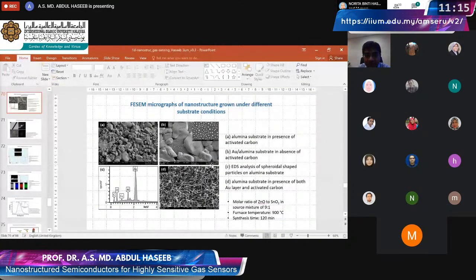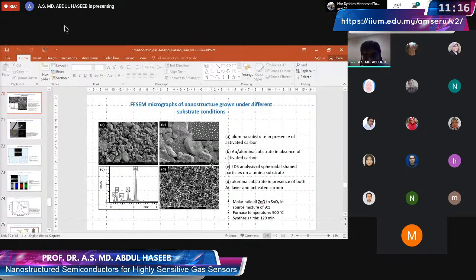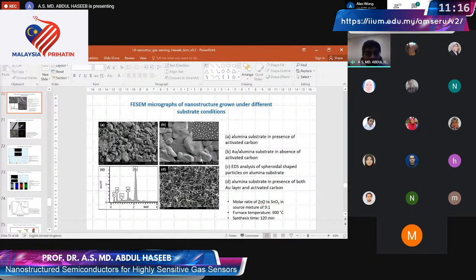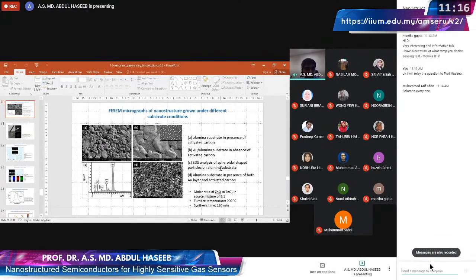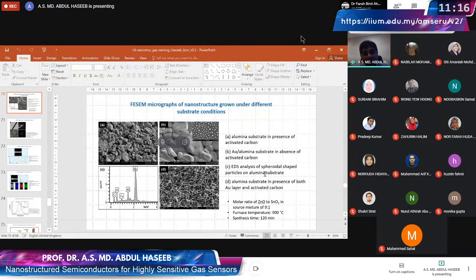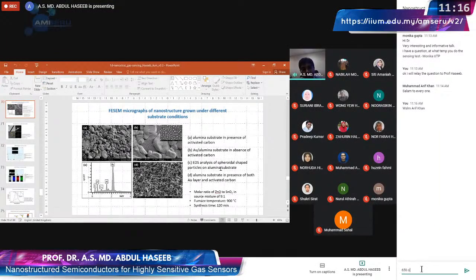Prof, there is one question from the chat. Hello, Prof. Very interesting and informative talk. At what temperature do you do the sensing test? The question comes from Monica from UTP. That is a very interesting, important question, and my apologies, I forgot to tell you this. If you saw some of the figures, the sensing temperature is high, because it has to be high in gas sensing with metal oxide semiconductors. We did the sensing in the case of titanium oxide at 650, because that was the optimum that we got. We get a high signal. We could go to other values, but the response would be lower.